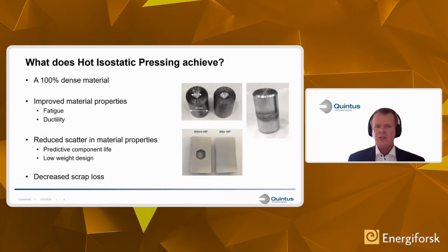Well, what does it achieve? Well, it achieves a 100% dense material by closing all the pores. It improves mechanical properties, mainly fatigue and ductility. It also reduces the scatter in the material properties, which makes component life more predictive. And eventually, it also reduces the scrap rate. And on the right-hand side, you can see this is actually a test that we did to show the effect of HIP. So we made a mechanically induced pore in a material, and you can see that that pore, which is probably about 1 centimeter in diameter, was completely closed after HIP. You can actually see the waist, which resembles the shrinkage of the part. That's a fairly large pore, so it's quite impressive forces in place.